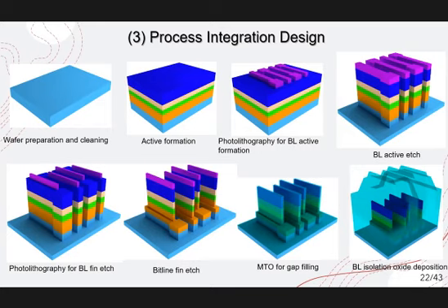The gap filling needs to be performed prior to the high-speed, high-temperature CVD. When we carry out PECVD or HDPCVD to deposit silicon dioxide at a fast rate to isolate the B-lines or some metallic connections, there can be some voids. So we need to introduce a very slowly depositing oxide deposition technique for the initial gap filling first. And that equipment is also installed in the ISRC.